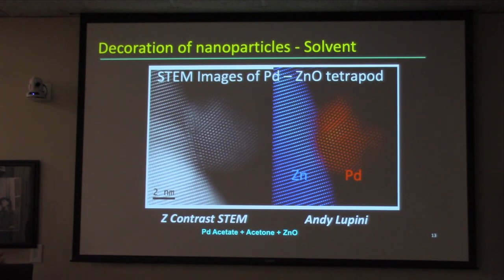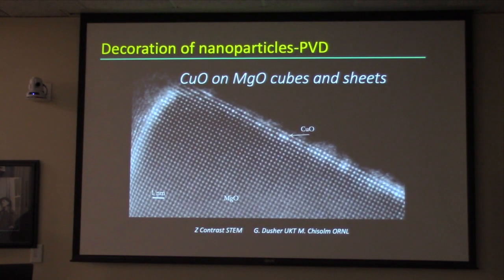But the other thing, so those are solvent-based. We use palladium acetate to deposit those materials. Remember, it's the guy that only knows how to read but doesn't know any organic chemistry. But it turns out that using magnetron sputtering, etc., we've actually now started to learn how to deposit copper in a solvent-free method on the interface.